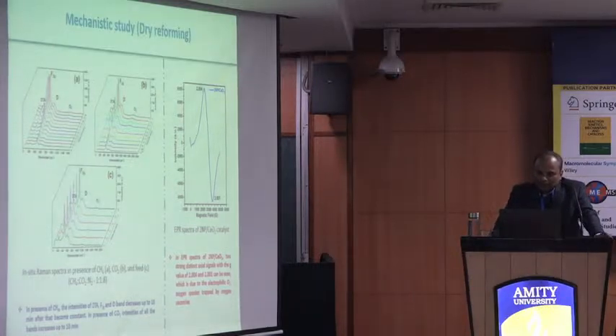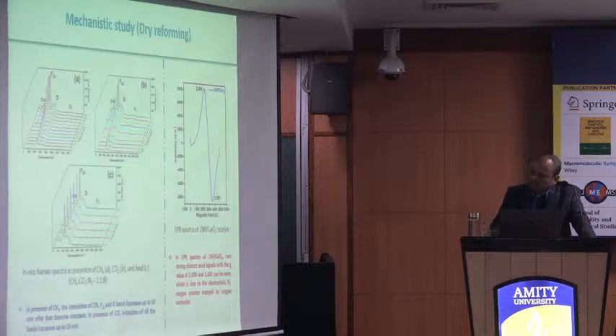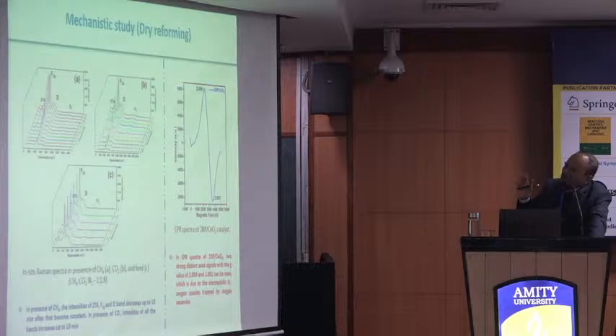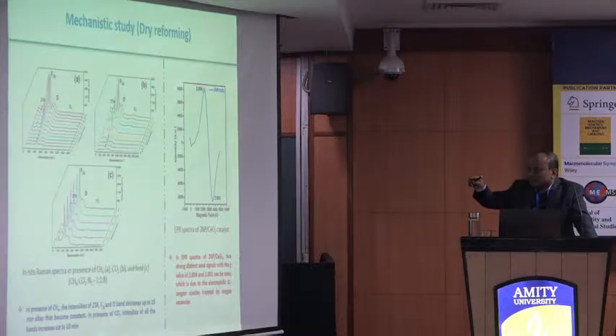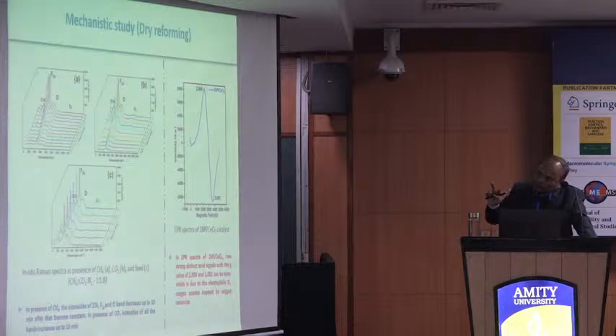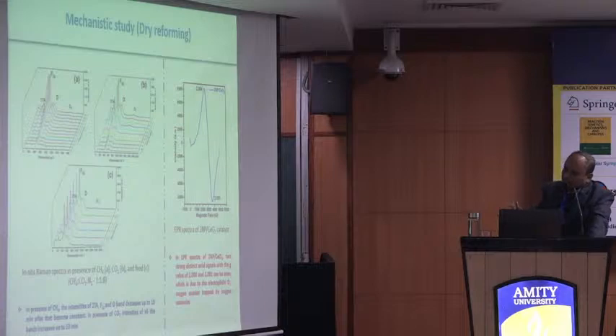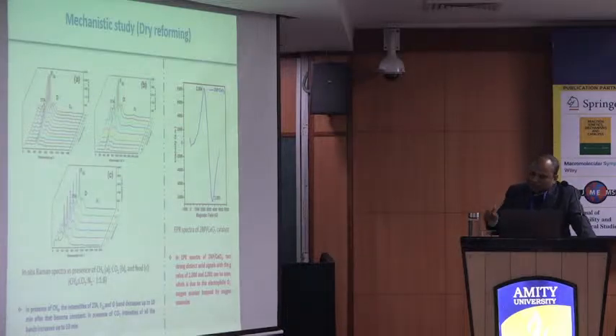Okay. And also we have done in situ Raman study. Here also you can see that the F2G band is shifted a little bit. That means the oxygen vacancy site is created more here. And also we have seen that with time, in the presence of the feed mixture, methane and CO2, the intensity is decreasing. That means this superoxide species is consumed during the reaction. And also we have done the EPR study, which is also showing paramagnetic behavior, that means superoxide species O2 minus is present in the EPR spectra.